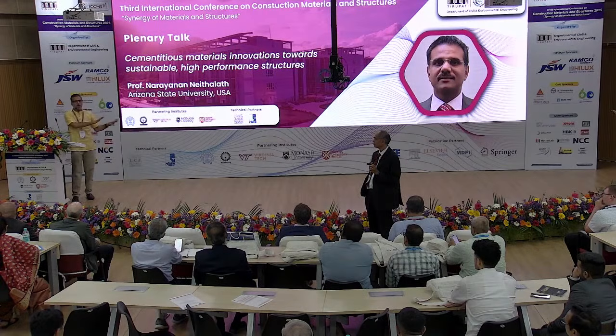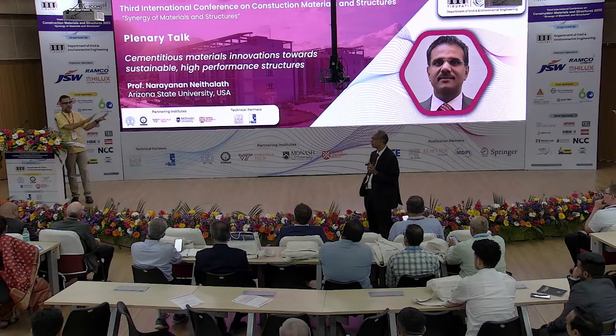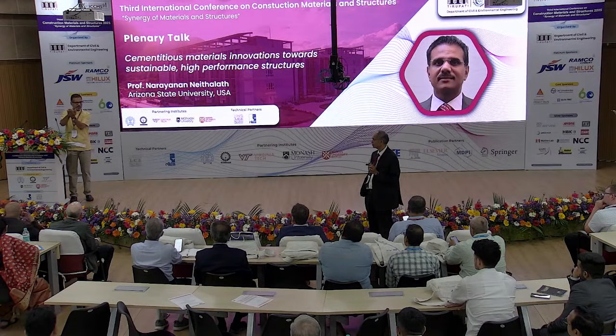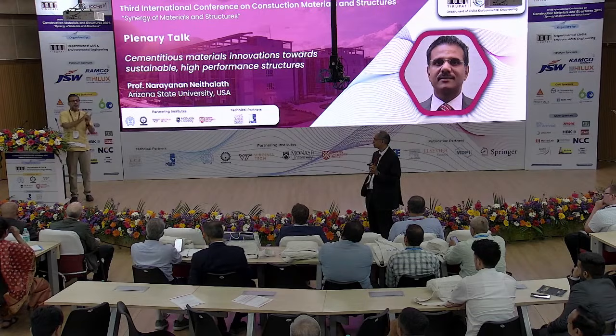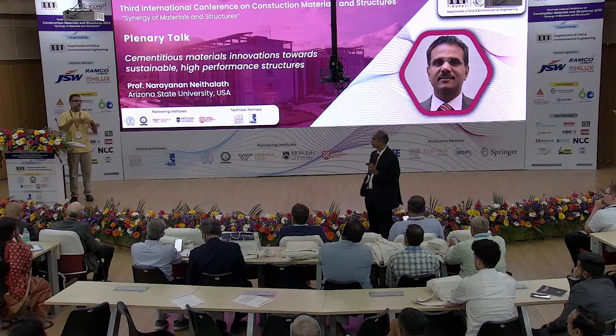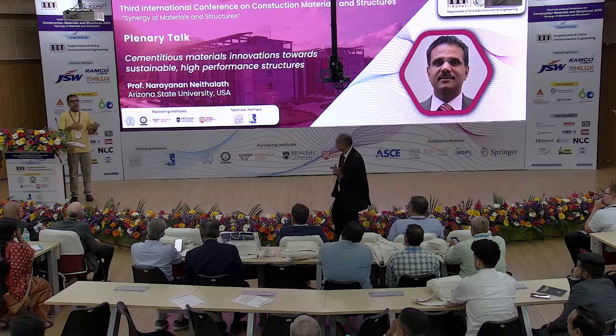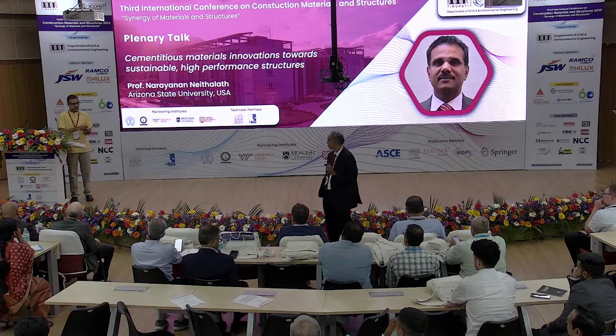Of course, forget about all the heat of hydration issues and shrinkage cracking that come along with it. But the fundamental idea is to increase the strength. So if you can increase the strength and reduce the cement content by 200 kilogram per meter cube, I have no problem. We should do that. And if that's the easiest way, that should be perfectly fine. But you're still using pure OPC clinker to do that.